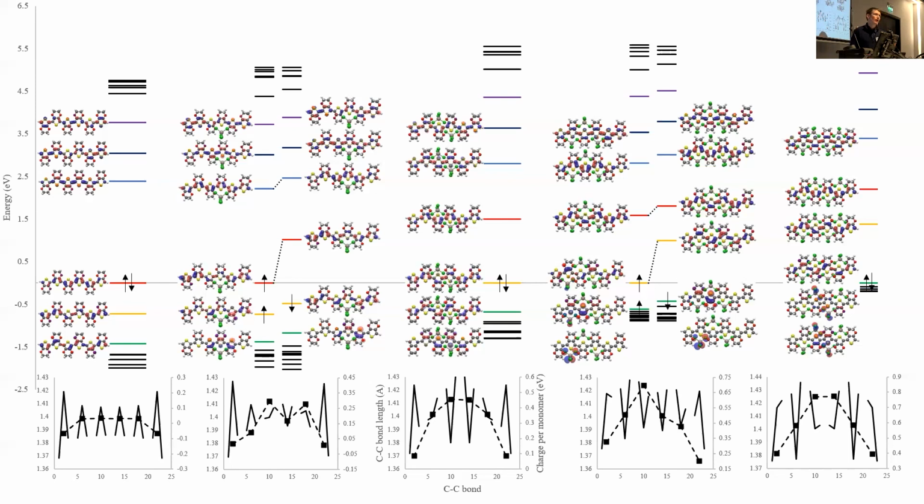The higher concentration of anions leads to much more overlap of those defects, and it's the defects themselves that travel down the chain. So that's by resonance. Those single and double bonds alternate so easily that they alternate with conduction, but the anions don't move. So it's sort of like ripples. They ripple down the backbone, if you like, by conduction of holes.